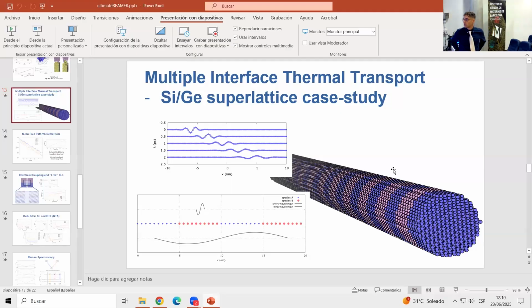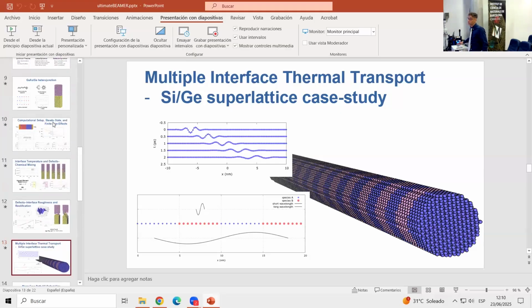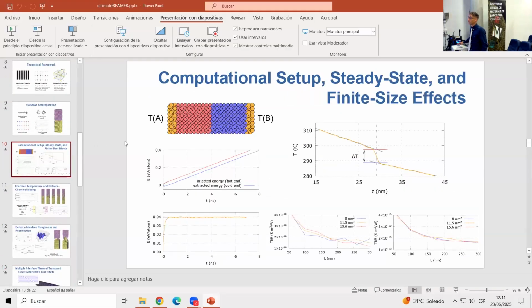Okay, I haven't stressed that much in the thesis, but the reason is that this sort of thermostating technique introduces some biases close to the thermostated zone. It introduces some non-physical phenomena because, of course, you don't get any velocity rescaling in the experiments. But it is very good because it allows energy conservation, and it is the preferred choice when you are not looking for equilibrium properties.